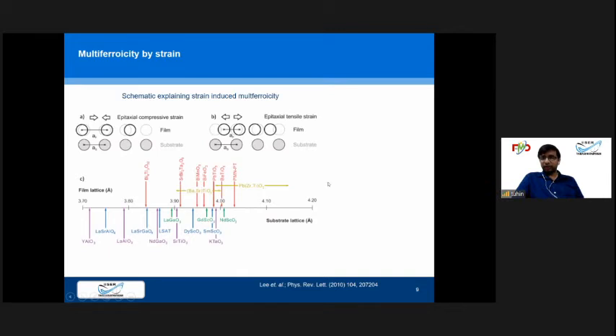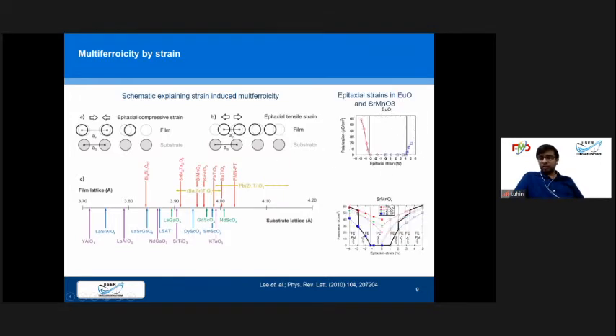So this is another example, of strontium manganese oxide, where by using this epitaxial strain, we can make them ferroelectric or paraelectric, or we can change their magnetic and electrical properties. So a phase change is possible by using this kind of strain. Then there are mainly two problems: the substrate strain only happens if the film is very thin, it doesn't happen in a very thick sample. And it's only in plane, there is no out-of-plane component of the substrate strain.